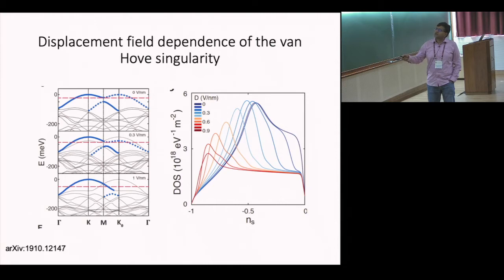Again, these are all within single particle theory. And you see that as you go from zero electric field to a small electric field, the valence band of one layer and the valence band of the other layer are no longer degenerate with each other. So you split them away from each other. And what this does, if you look at the density of states of the top Moiré band, which is where all this physics happens, this is what the density of states of the top Moiré band does as a function